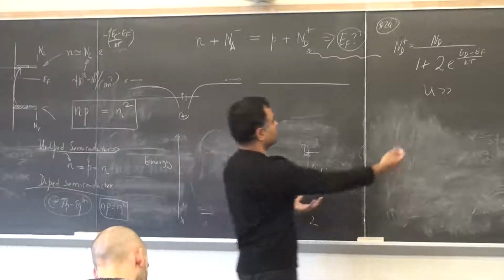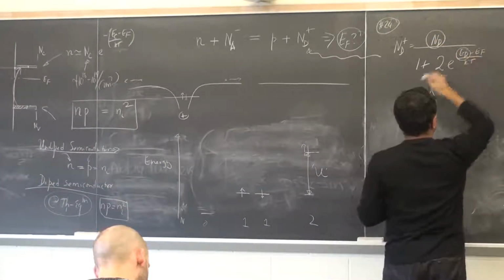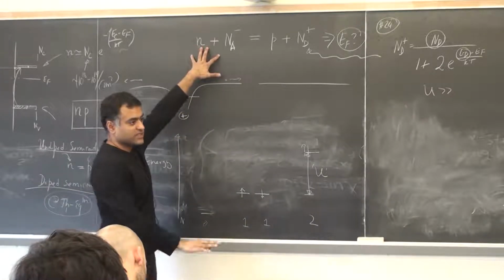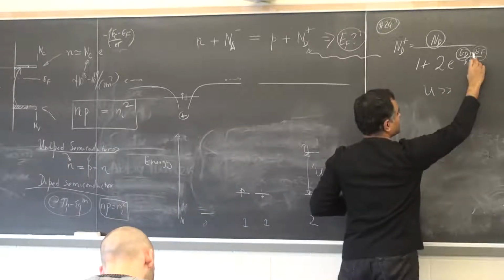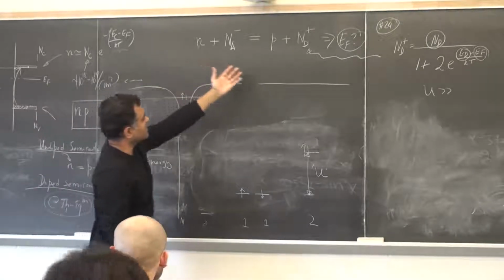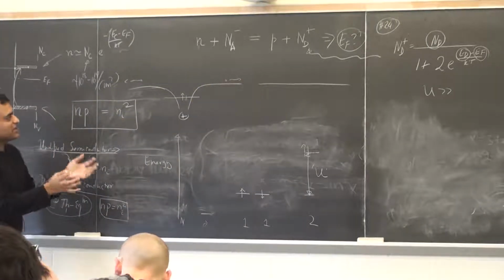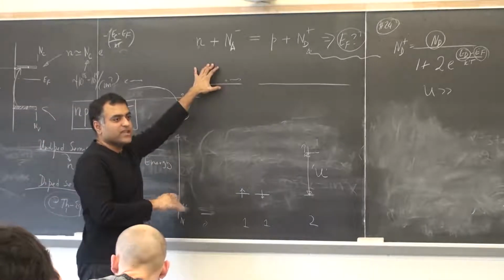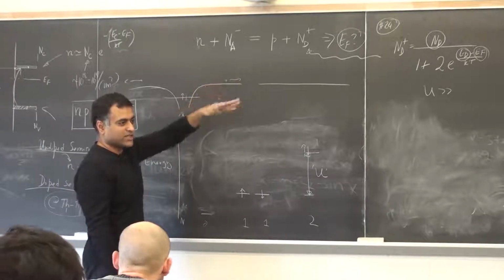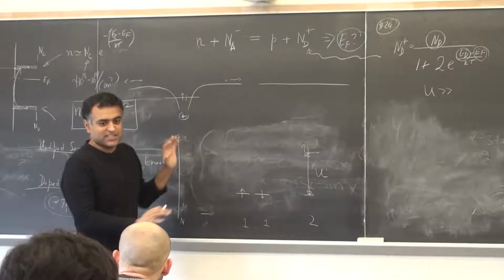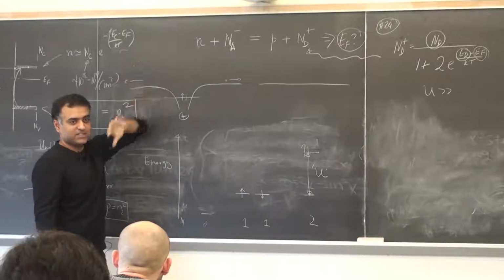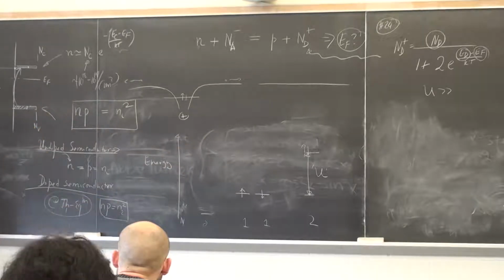So what I've given you in the problem are things like what is the doping density, what is the donor activation energy, what is the acceptor doping density. So essentially, you just solve this now, right? And your only unknown in this equation would be the Fermi level. So that's very fine. And if you write a little code for it, that will take care of any semiconductor you may ever encounter. You can just change the band gap, the doping density, activation energy. You will always get the carrier density right away from there. So this essentially solves the doping problem completely for semiconductors, once you solve this equation. Does that make sense? Yeah.